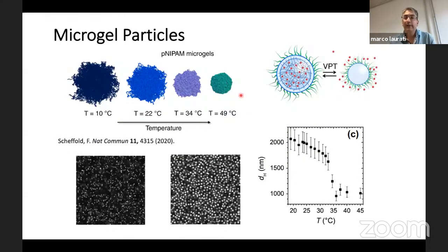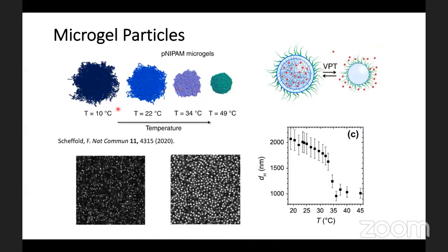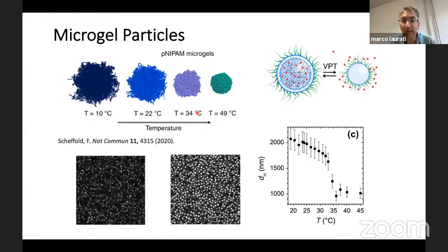So actually, we studied the classical microgel system, so NIPAM microgels, which are these essentially thermally responsive particles, which undergo a hydrophilic to hydrophobic transition when you increase the temperature of the system, and this transition, of course, induces a shrinking of the particle size, which has been used among, of course, other applications. For example, in something like drug delivery, it's a mechanism that you can use for releasing things that are trapped inside the particle at smaller temperatures. When you increase the temperature.